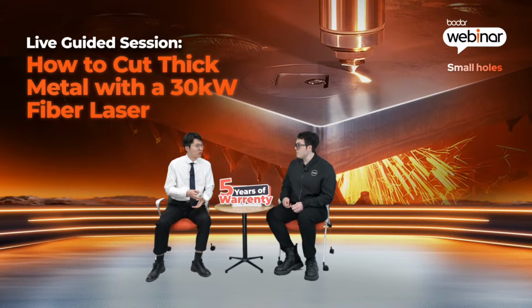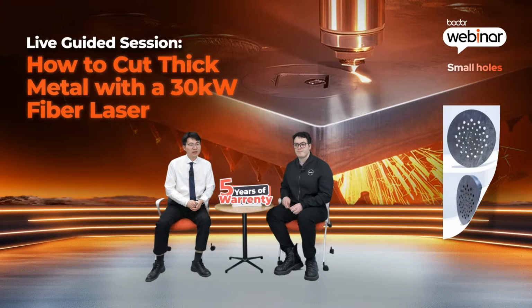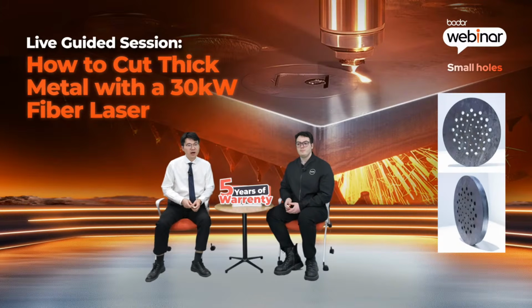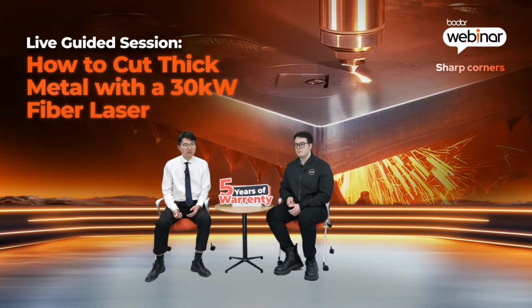And let's look at a real example. This is a 500 millimeter diameter circular plate in 25 millimeter thick carbon steel, with 50 small holes ranging from 4 to 10 millimeters. All processed directly by laser, no secondary operation needed.